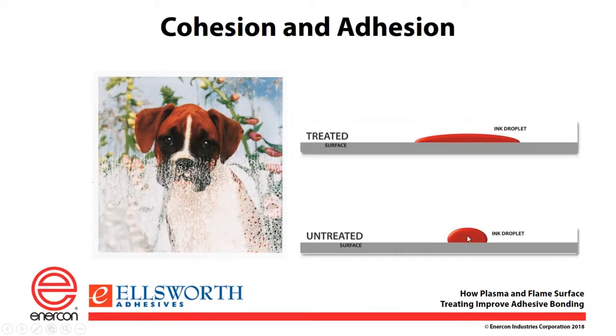When you wax the windshield of your car, what you're doing is you're decreasing the surface energy so that the cohesive bonds between the water molecules are stronger than the bond between the water and the surface. So that water will bead up like that and it rolls off. When we treat a surface, you're increasing the surface energy so that the water, the ink, the adhesive will all wet out. And in the printing application, the picture of the dog over there, you can see that if you're using adhesive, you want a nice, active surface in order to allow that picture to stay on there and you won't be able to remove it or scratch it off like you would if it was an untreated surface.